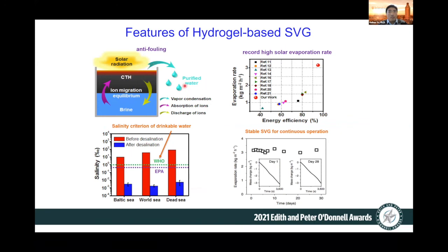So given this structural design, we can enable this very long-term water desalination with record high solar evaporation rate. We can achieve over 3 kilograms of water per square meter per hour of evaporation rate. And you can see effective removal of the salts with various salt concentrations, Baltic salt, world salt, and the Dead Sea. So you can see over 4 to 5 orders of magnitude of the salt can be removed, and then the distilled water actually more than meets the drinkable water criteria.